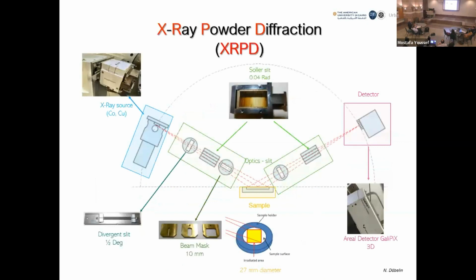After that, I started to analyze in great detail the mineralogical and chemical composition of the powder, because in this way I was able to understand the reaction between the water glass and the powder. In order to do that, I work a lot with X-ray powder diffraction. I worked a lot with this kind of instrument in Padova, and I'm trying to do the same in Vienna, where we have a powerful center, but unfortunately they use this kind of instrument for different purposes, especially in catalysis, and they are not used to working with cement and polycrystalline phases such as mortar and so on. And so I'm trying to fix everything in the best way possible.